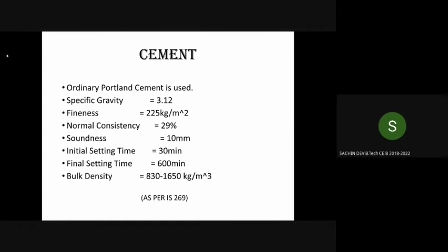Next we use ordinary Portland cement for our construction purpose. As per IS 269, the properties of ordinary Portland cement are: it has a specific gravity of 3.12, and it has a fineness of 225 kilogram per meter square. And the normal consistency of the cement is 29%, and it provides a maximum soundness of 10 mm. And the initial setting time of the cement is 30 minutes, and its final setting time is 600 minutes. And the cement has a bulk density of 830 to 1650 kilogram per meter cube.